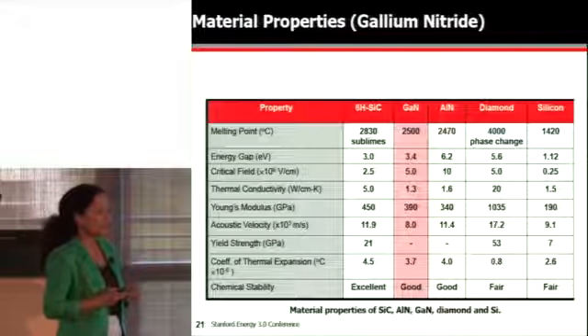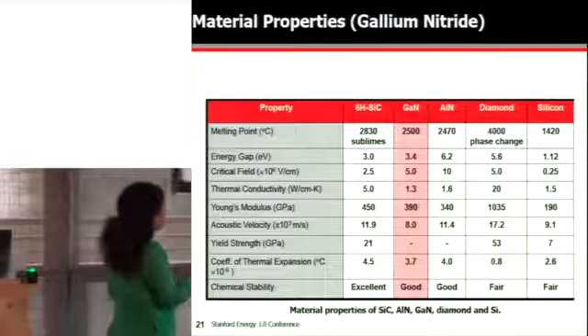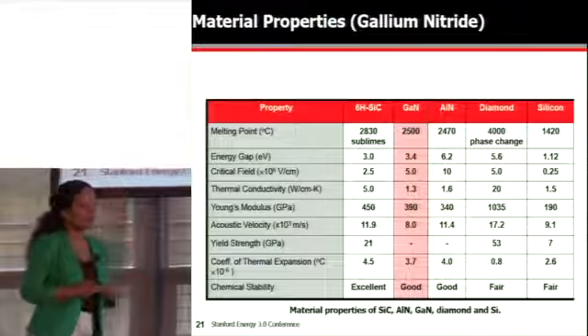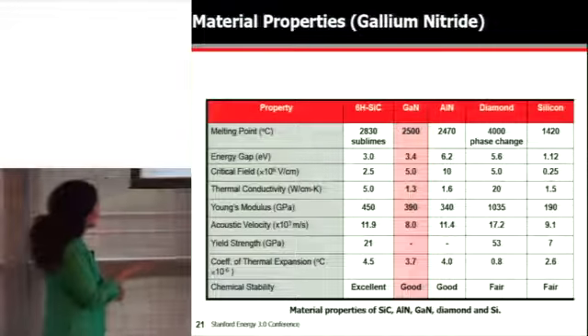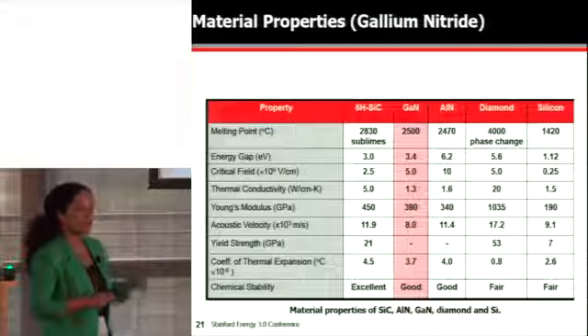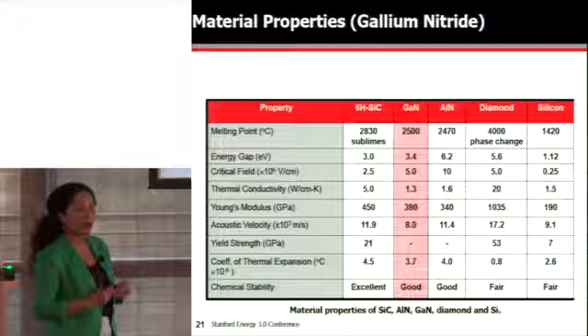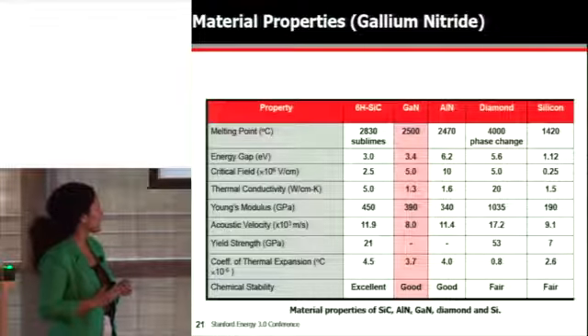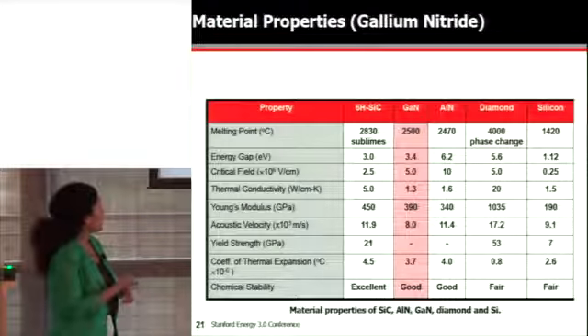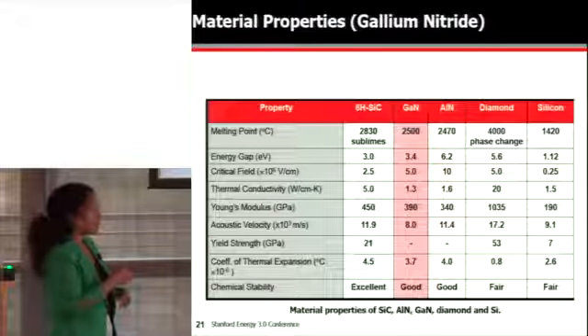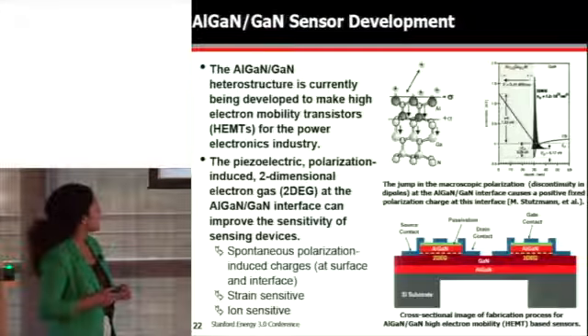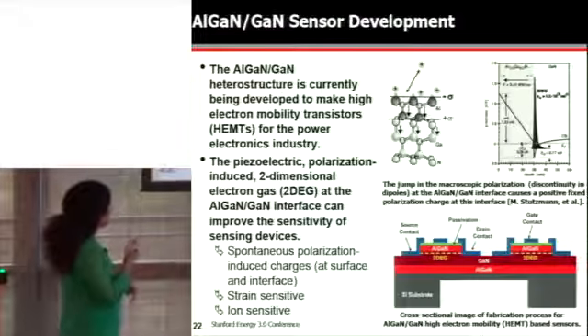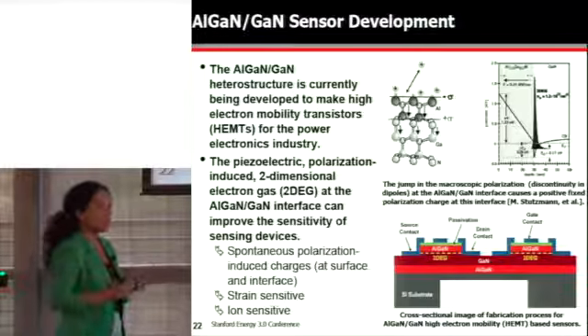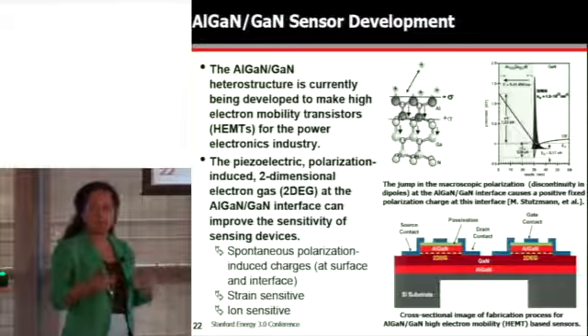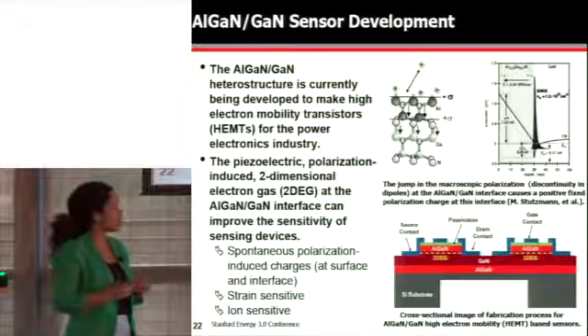It's another wide bandgap ceramic material. You can see here the melting point is 2,500 degrees Celsius. Also the bandgap is slightly higher than silicon carbide. So again, we can think about having functioning devices at temperatures as high as 1,000 degrees Celsius. It is also a piezoelectric material, and so you can think of creating new types of devices with this platform. Gallium nitride is also an emerging platform in the power electronics community due to its temperature handling and ability to handle very, very high voltages.